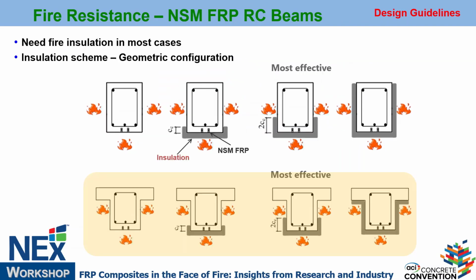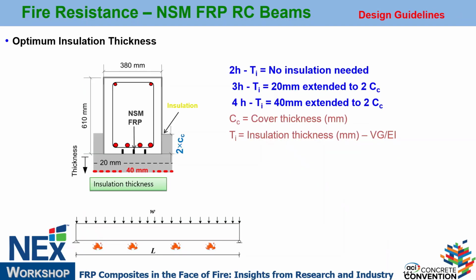Now, what about NSM? With NSM, you can get away without fire insulation sometimes, and most of the time up to 2 hours, provided you place the bars only at the center, not at the edge, not at the corners, right? And for insulation, this is the most effective way. Again, 2 times the concrete cover thickness, just like before. And how much you need is given here, very much similar. You need a certain cover thickness to get 2 hours, 3 hours, 4 hours. You can achieve that.